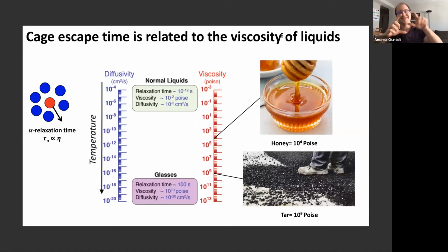But let's discuss again this idea of escaping the cage. Now in a fluid, in a liquid of any kind, escaping the cage is some sort of relaxation process called the alpha relaxation. And the time needed to escape the cage, which is the alpha relaxation time, tau alpha, is related to how the liquid flows. So it's actually related to the viscosity of the liquid. And the crazy thing is that for liquids, if you start reducing the temperature, but you avoid crystallization, so you're still in the liquid phase, this relaxation time will go from 1 picosecond for water, for example, up to 100 seconds. That's 14 orders of magnitude of change in the relaxation time, often in a very narrow gap in temperature.